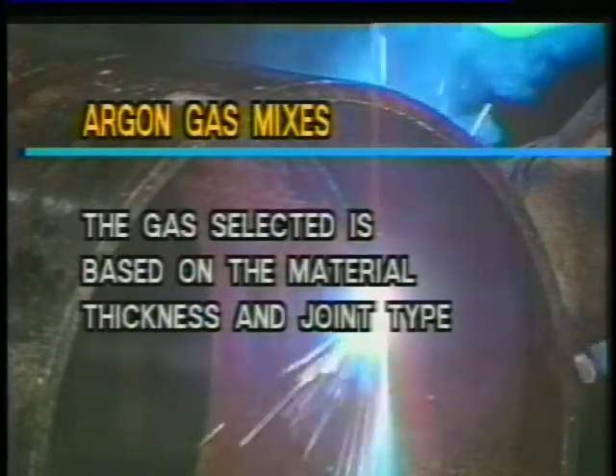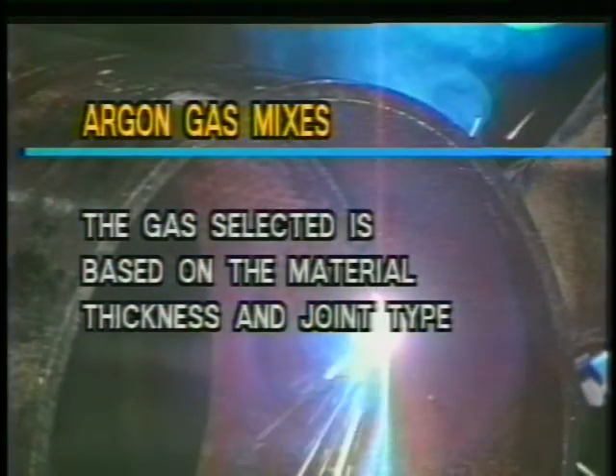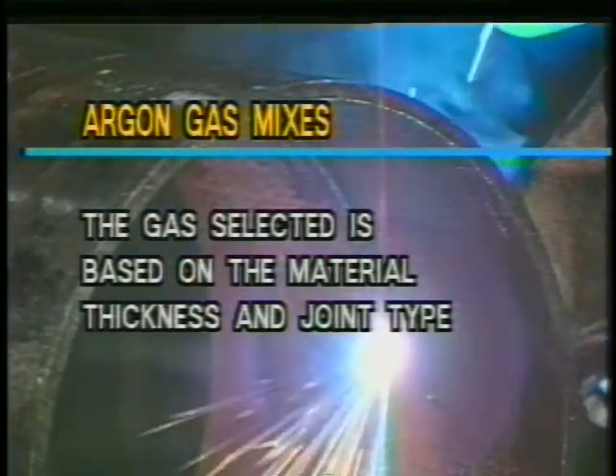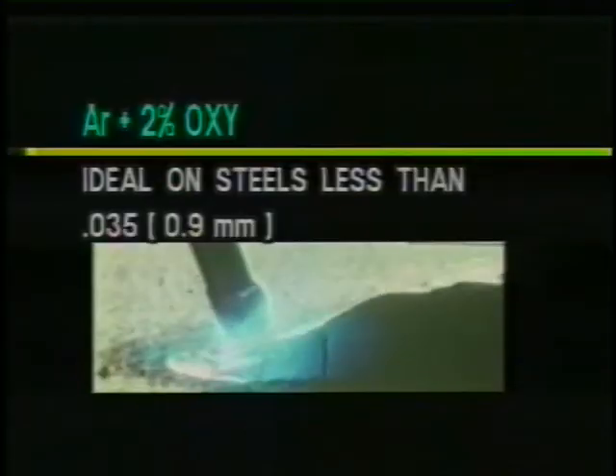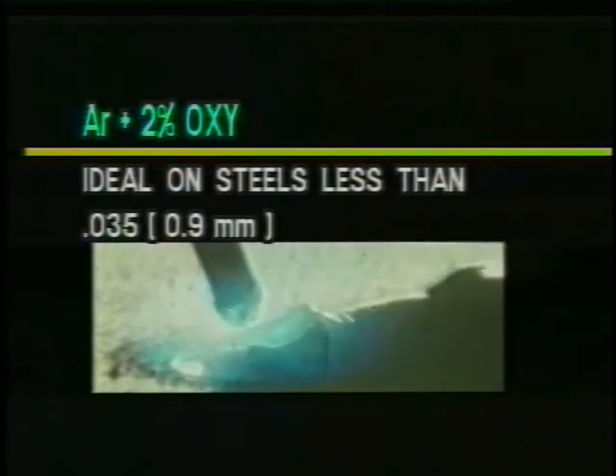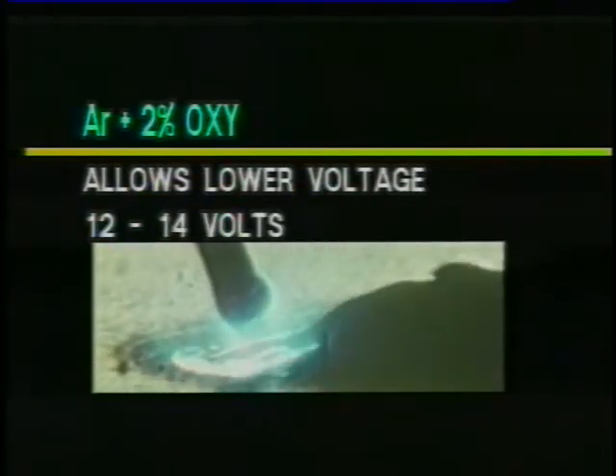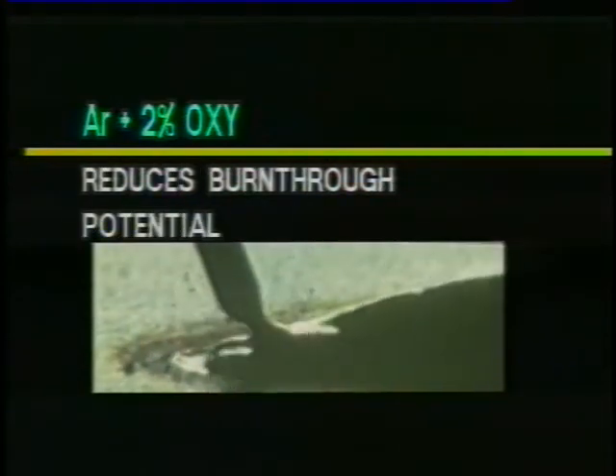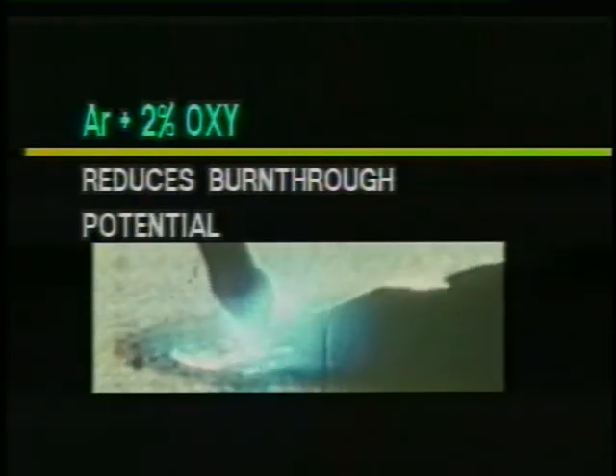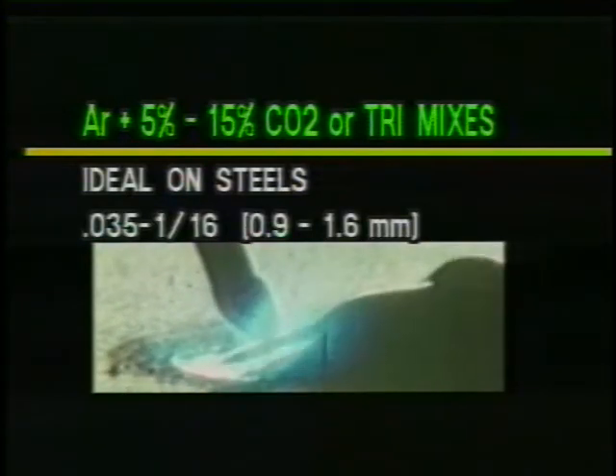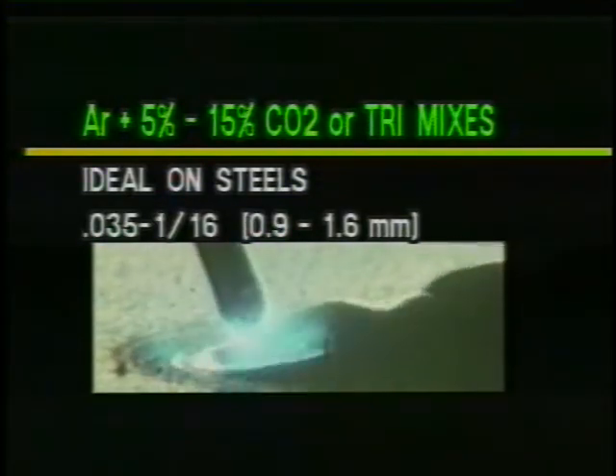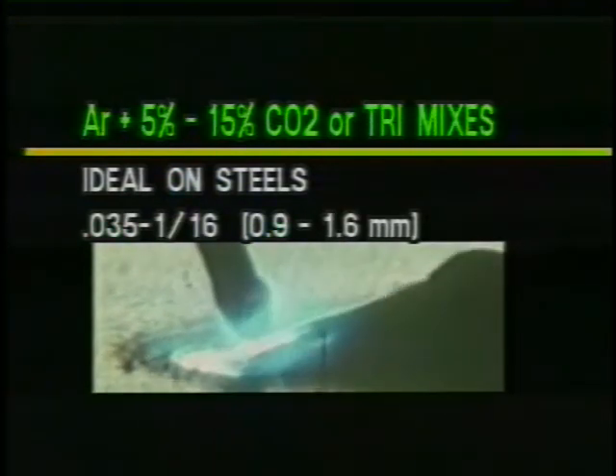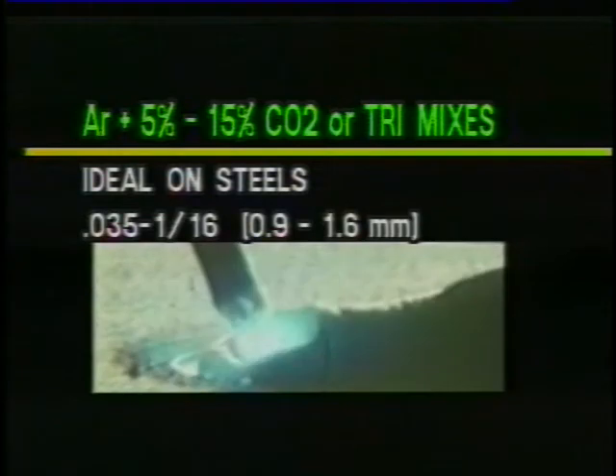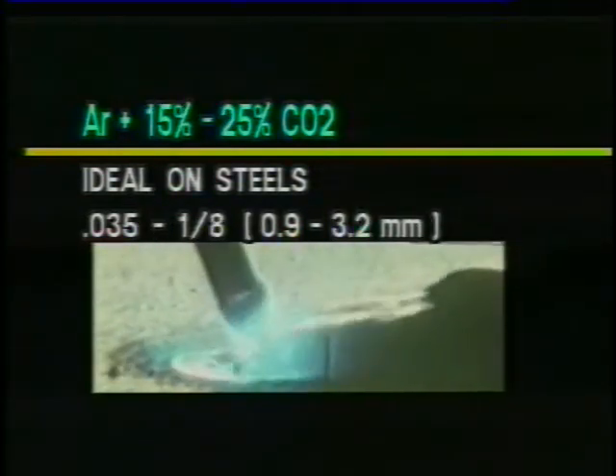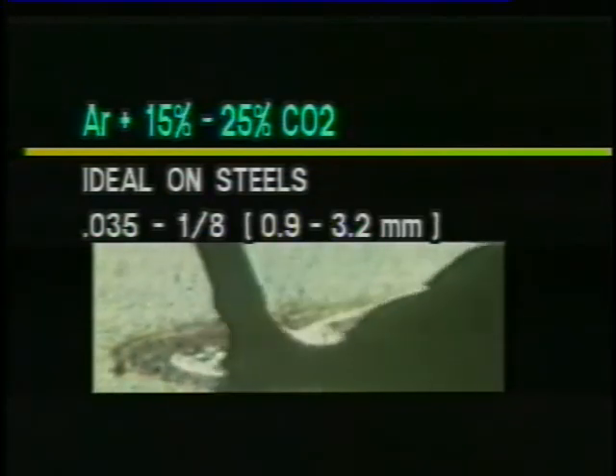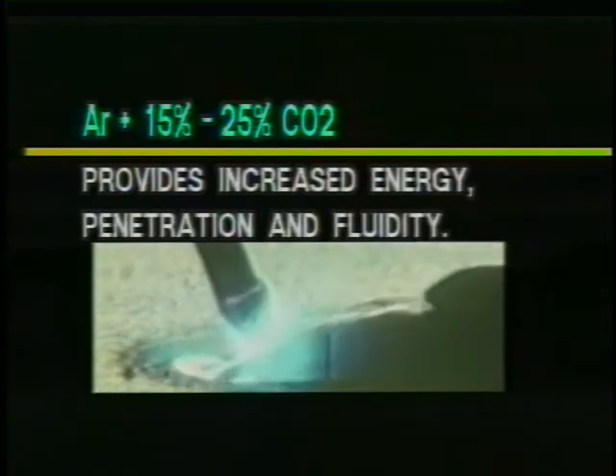The material thickness, joint type, and weld position are the prime factors in considering an optimum gas mixture for short-circuit welding. On metals less than 035, argon oxygen allows the use of lower voltages, which reduces burn-through potential and minimizes damage to coatings on the opposite side of the material. Remember, the thinner the sheet metal, the less heat it requires from the welding gas. These mixtures provide the required level of arc energy with optimum arc stability. For increased arc energy, a slight increase in reactive gas improves penetration and weld fluidity.